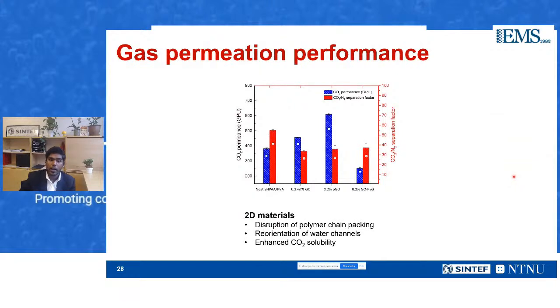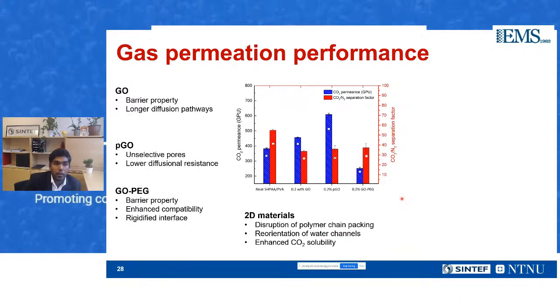With that, we added the graphene oxide, porous graphene oxide, and GO-PEG at a very low loading of 0.2%, because the 2D structure of graphene oxide can volumetrically disrupt as much as possible. So here we have disruption of polymer chain packing and reorientation of water channels, which is what we wanted for facilitated transport membranes. You also have enhanced solubility of CO2. On the other hand, graphene oxide still retains its barrier property and leads to longer diffusional pathways for CO2.